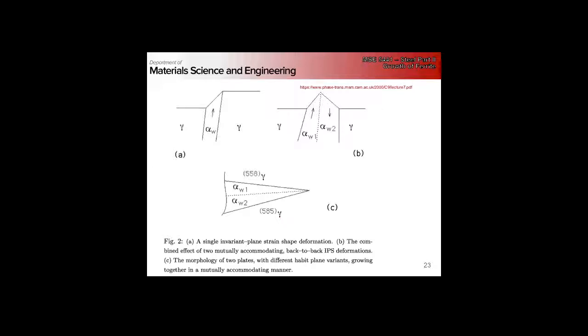And this is a displacive transformation, and so there's a shear associated with this. So you can imagine if I'm nucleating and growing, and I've got a shear, this is going to give me this sort of - if I have a single plate here and I shear, I now have a jog on my surface, or in my crystal, that this needs to be accommodated. And if this is in a polycrystal, I've got neighboring grains that are pushing back on this. As this grows, that shear gets larger and larger.